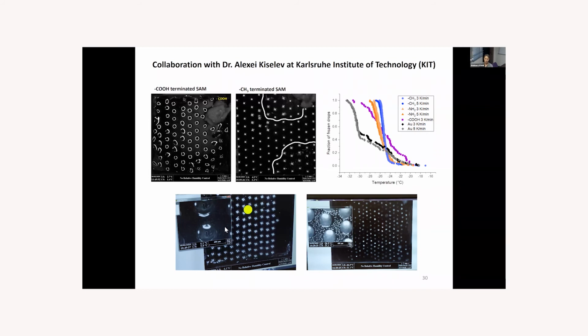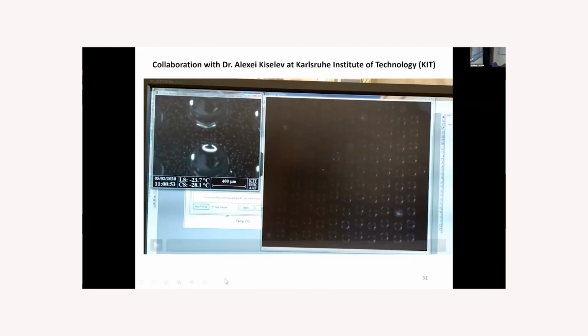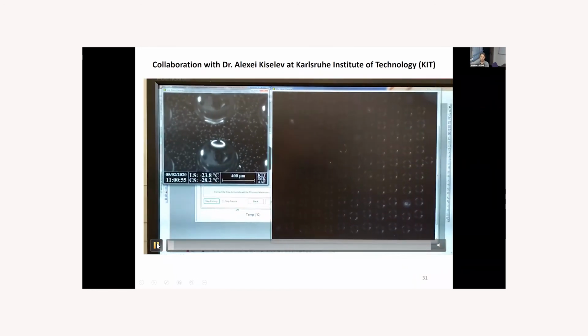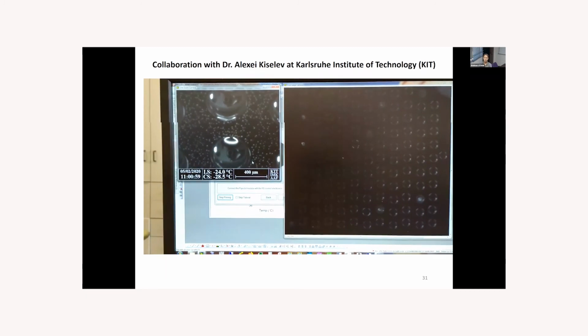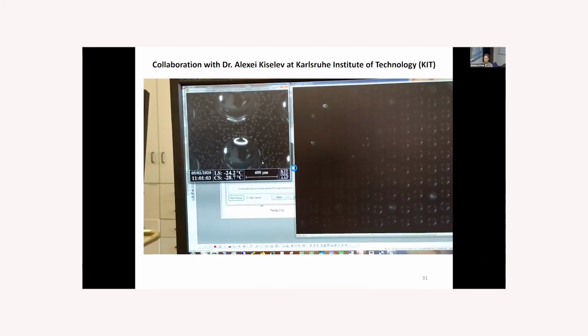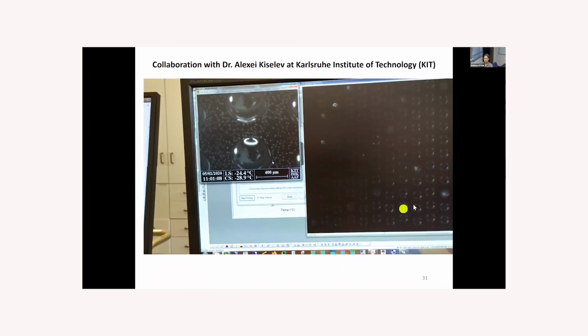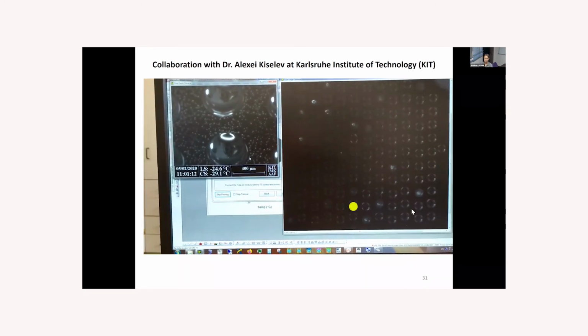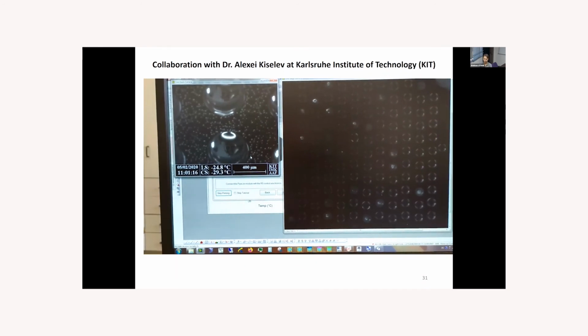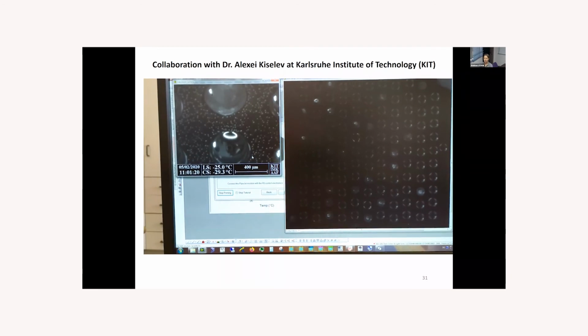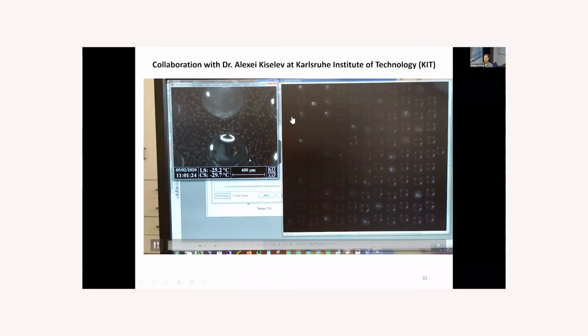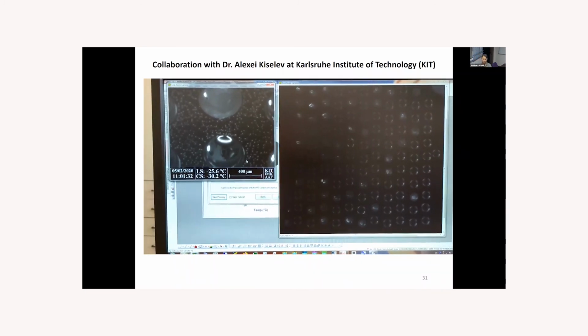Here you can see how it looks when the water droplets are not frozen, and here you can see when they are frozen. It looks quite different. Here, as they zoom in, you see the frozen droplets. I would like to show you now the video I made with my phone of the freezing of these water droplets. This is, I think, the methyl group terminated SAMs. And you can see that the droplets start to freeze one by one, not even close to each other. So this means that the experiment went well, and there was no interconnection between the droplets, so the results are very good, and there are no problems with the measurements.